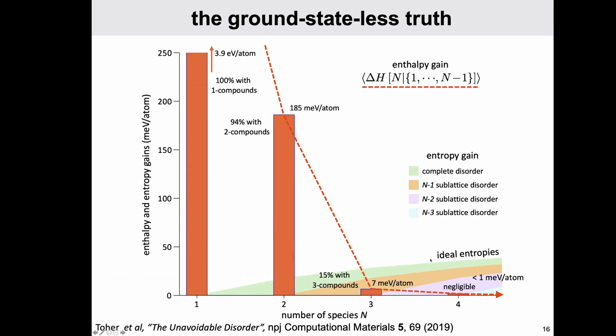This is if everything were disordered, if everything minus one species were disordered, minus two species, minus three. So practically, when you have around four mixing species, pretty much everything is disordered. That's why when people mix four, five, six species, most likely the system is disordered and a stable configuration cannot be found. But even if it were found, it would not really be stable with respect to temperature, because it would dissociate very easily.